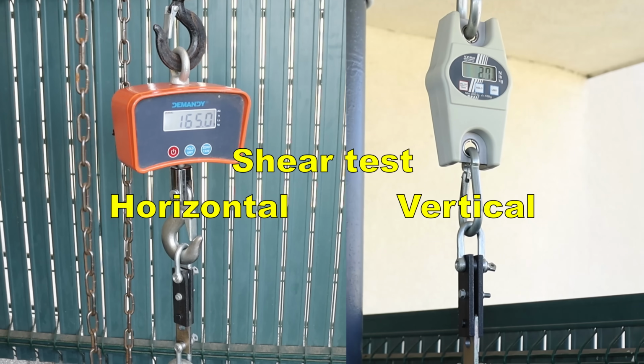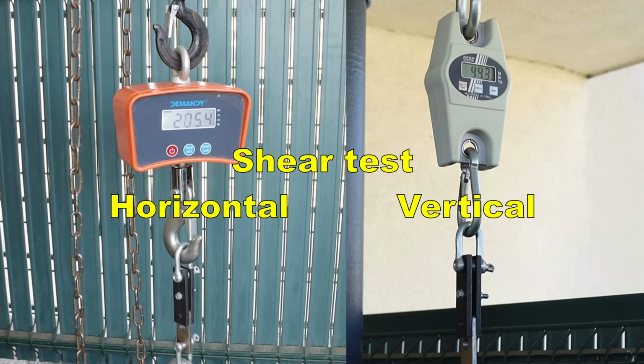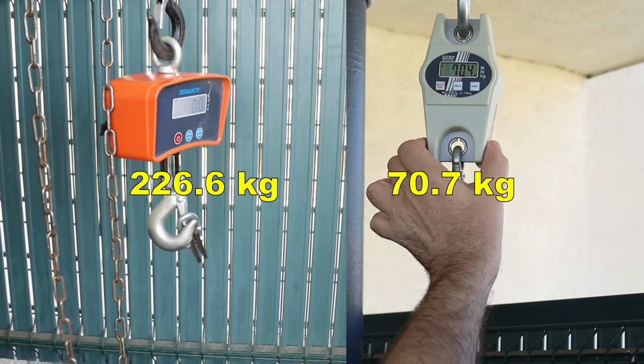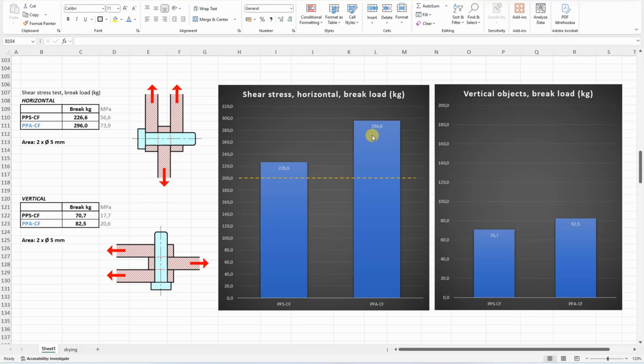Shear test side by side, horizontally and vertically printed test objects. Yes, compared to the PPA, this filament is weaker, but look at this, it is very rare that I have to use that stronger crane scale because my main scale can measure up to 200 kilograms. So this is very strong too, printed in horizontal position. Printed vertically, we have that weakness of the layer adhesion. Let's say this is still acceptable.